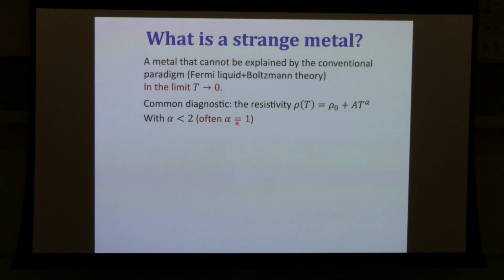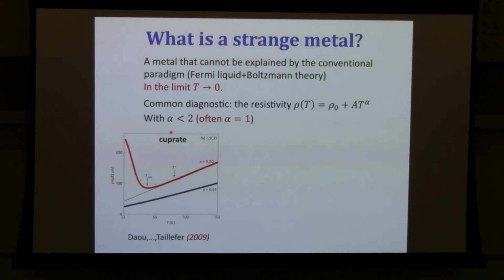That means that the resistivity is linear as a function of temperature down to the lowest measurable temperature, but not always. I'll show you some systems where this deviation manifests itself in some other low temperature behavior, which is different than T squared. Okay, so here are some famous examples. This is a cuprate, a high temperature superconductor, and this is what happens when you suppress superconductivity by applying a magnetic field. So the resistivity continues down linearly to the lowest measurable temperatures.